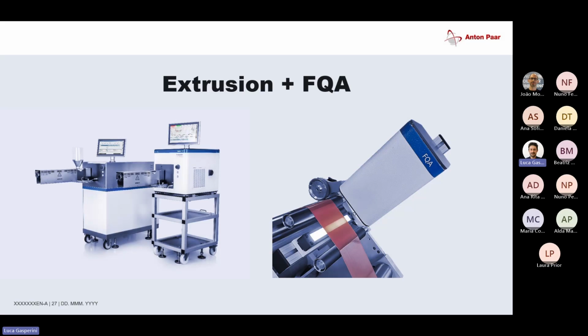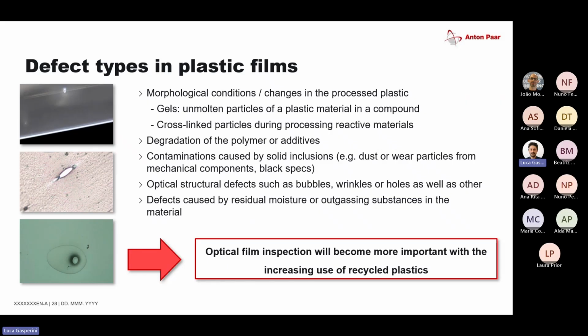You can observe the quality of the film continuously with a camera which is attached to a winding system for films. So what it can do, it detects different kinds of defects in your foil. The software usually differentiates between holes, black spots, and gels. So gels are usually, for example, unmolten particles included into the film.